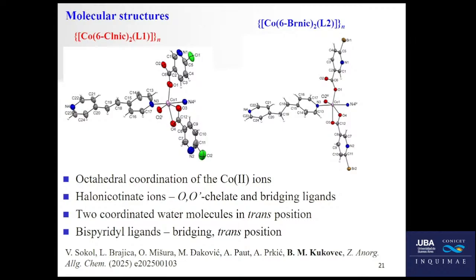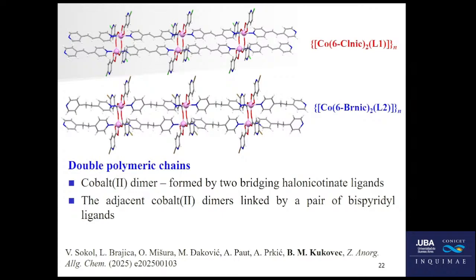Since we didn't do this synthesis in water, there are of course no water molecules, either coordinated or lattice molecules. When you look at these two compounds, you see that this can be called either a ladder or a double chain. I call it here a double polymeric chain. Two cobalt ions are bridged by two bridging halonicotinate ions. This one is bridging, the other is bridging. We also have two chelate ones, each attached to only one cobalt. In this way we get the dimer, and these dimers are further connected by bipyridyl ligands. Each dimer is connected by a pair of bipyridyl ligands.